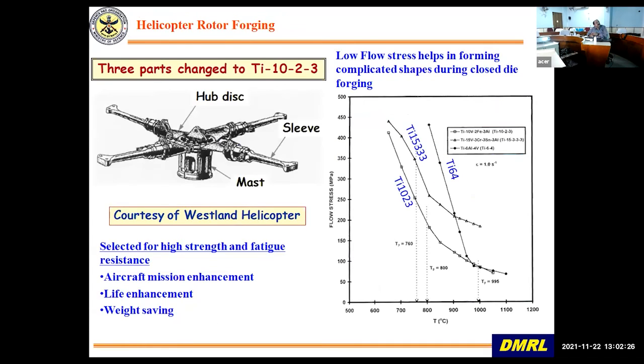Now, here again, helicopter rotor masts and rotors are also made of these kinds of Ti-10-2-3 like alloys. Why they are attractive is because they have lower flow stress. Here I plotted the flow stress versus temperature, from literature, I did not plot it myself, for Ti-15-3-3-3 versus Ti-6-4 as a function of temperature.